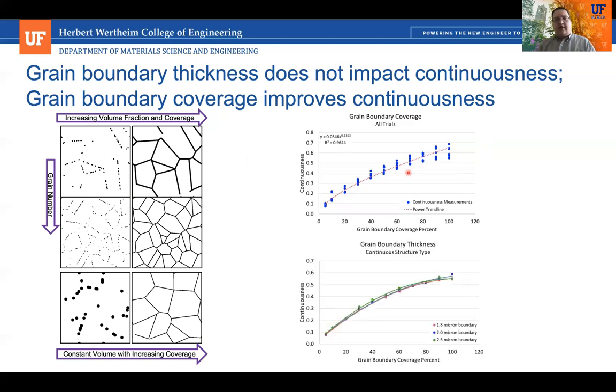If we just look at the impact of the thickness, so compared to this very thick, thinner, and then quite thin, we don't see a huge impact of that. And so though the coverage matters, if you thin it out to try to minimize the overall volume fraction, you're not going to significantly decrease your thermal conductivity up to a point. There will eventually come a point where you're thinner than the photon mean free path, or the electron mean free path if it's a metal, and then you're not going to get that same benefit.